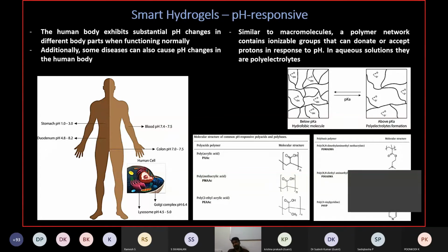So you do a kind of dissociation of the groups, and you should be very clear about the pKa value. The pKa value is the exact pH at which the dissociation takes place perfectly. It should be 50% of one form, 50% of the other form, and the pH corresponding to that is called the pKa value. You know, that should be known. The pKa changes for different structures. For one structure it may be one pKa, for the other structure the pKa may be different, and that again can be different under the condition of light also.